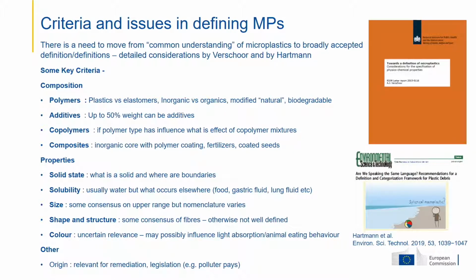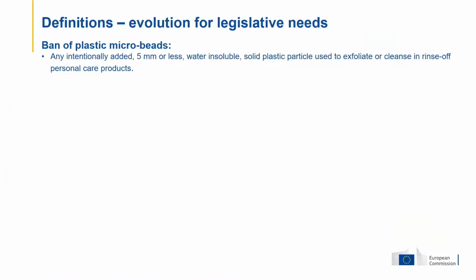This is understandable, as the driving concern of microplastics is generally an environmental risk due to the long-term build-up, which would not necessarily be problematic with truly biodegradable materials. However, with degradation time scales being of the order of weeks or months, they may disappear quickly from the environment, but may still produce many short-lived particles which will still have a lifetime of relevance to living organisms.